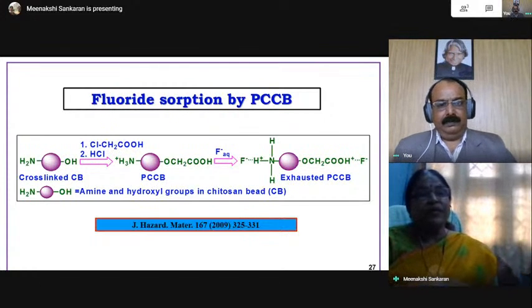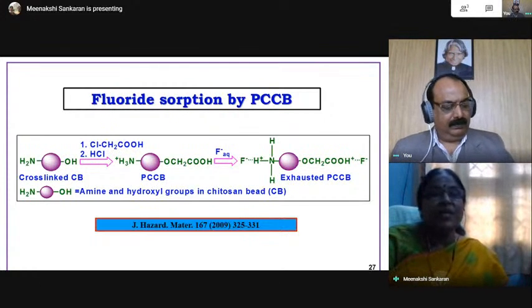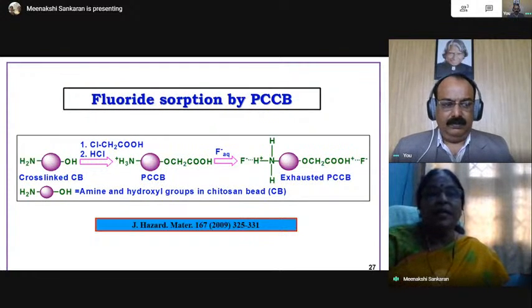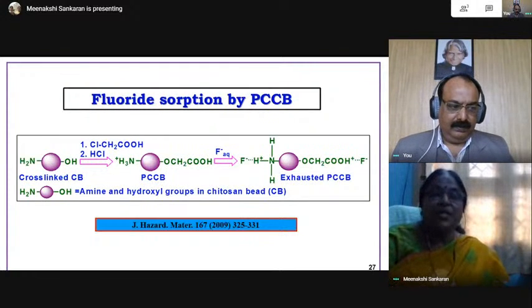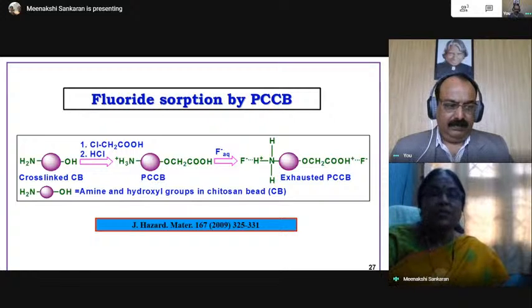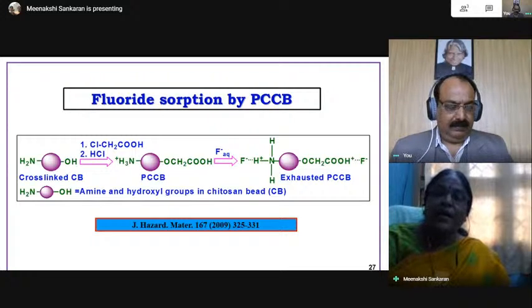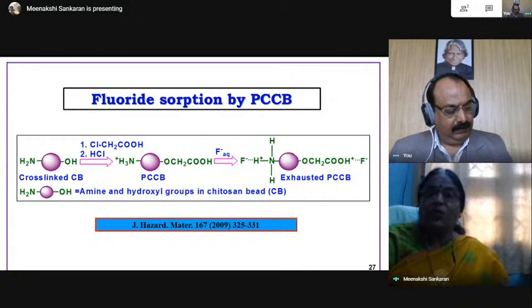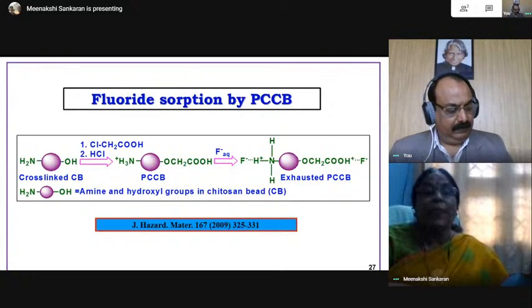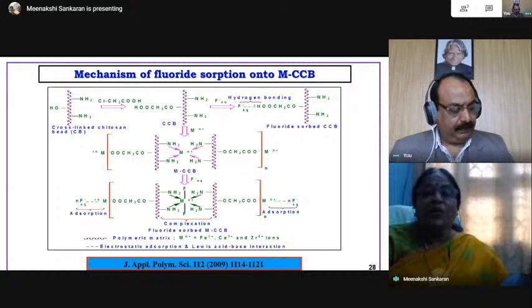So we have separately done carboxylation and protonation. Here we have done both amination and carboxylation. Now this protonated and carboxylated chitosan beads showed higher efficiency for fluoride removal. These three modifications we have made and removed fluoride. And we have also incorporated metal ions into this chitosan.